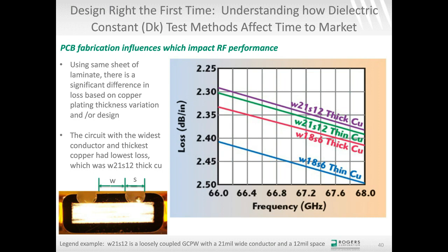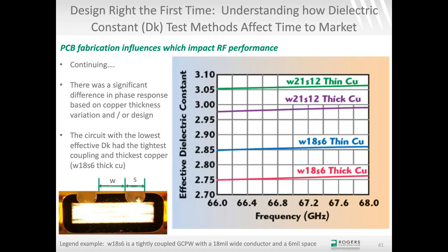And my thought there is when the copper is thick, now the sidewalls between the signal and the neighboring ground planes are taller, and that means you're making more use of the air. So electric fields are more in the air, and air is the lowest loss medium, so you're going to have lower insertion loss. Now, the same type of study was done looking at the phase response and then measuring